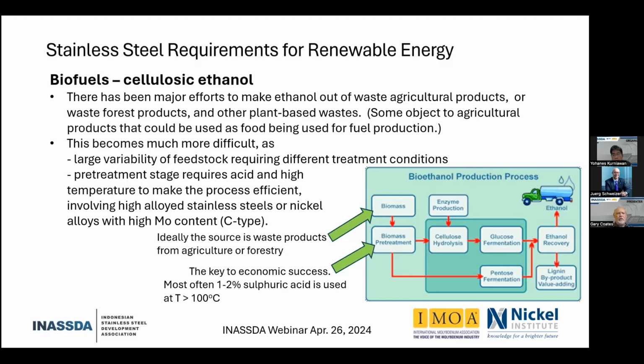We need acid and high temperature, so we were looking at corn stover. That's the waste product from when you grow corn, and you use 1 or 2% sulfuric acid. The higher the temperature, the quicker the process happens. And so to make it really cost efficient, you do need a higher temperature there, and that involves highly alloyed stainless steel, perhaps the 6-moly stainless steels or 904L, or nickel alloys. The most effective use at the highest temperature was with the high molybdenum C-type alloys. But once you get beyond the pre-treatment stage, it's a relatively less corrosive process as the temperature drops. And so therefore the rest of the plant is normally done with the 304L, 316L type materials, or perhaps some use of duplex.